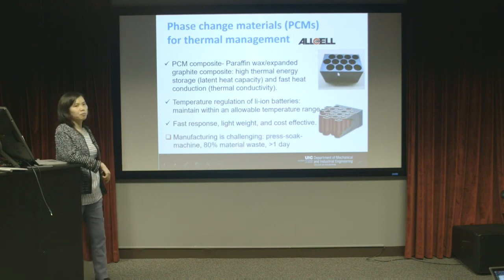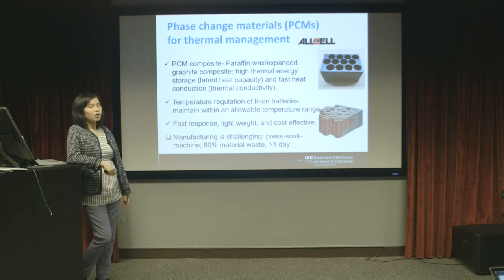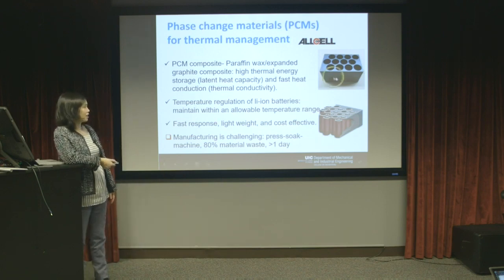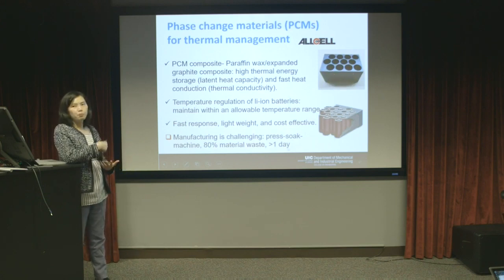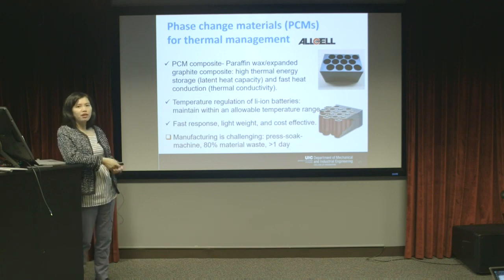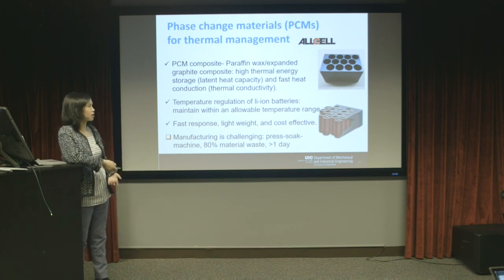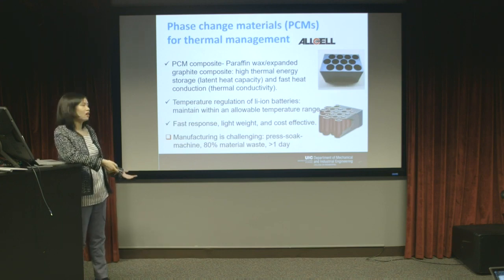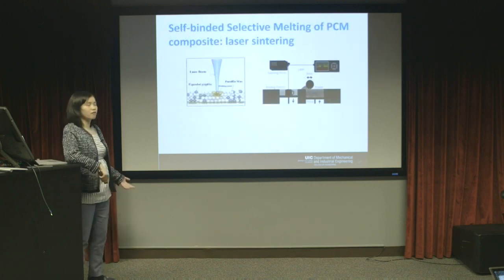However, they have a big problem, which is material waste. The way they fabricate it is press, soak, and then cutting and drilling. During this process, they have a big material waste, which can be up to 80%. And also, the fabrication cycle is very long. They need days to fabricate the product. Of course, if you don't change the design, then it's okay. But if you change the design, or if you want to do some quick tests, then the fabrication time is an issue. So that's why they think about additive manufacturing.